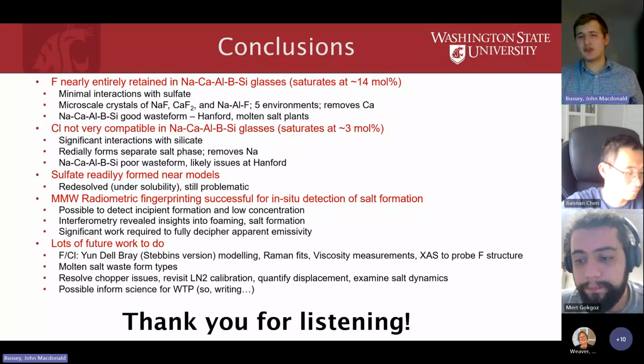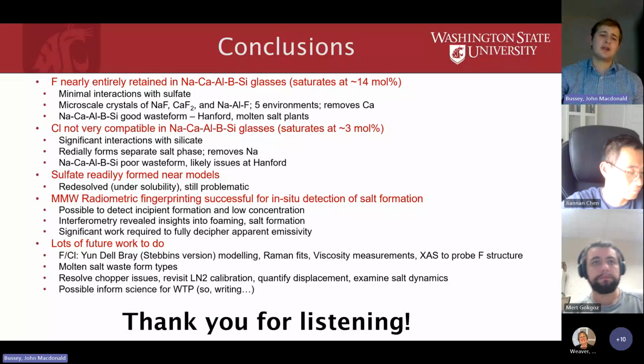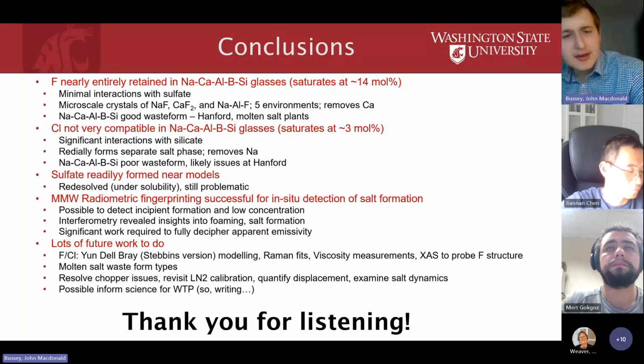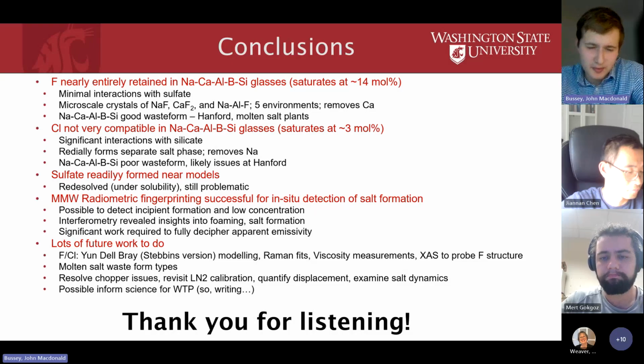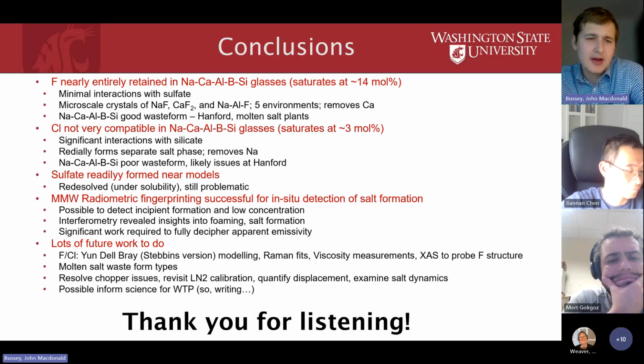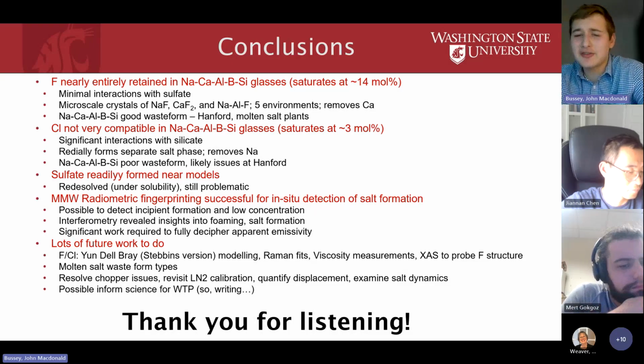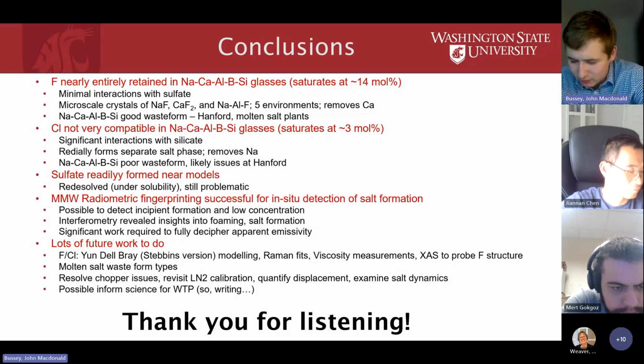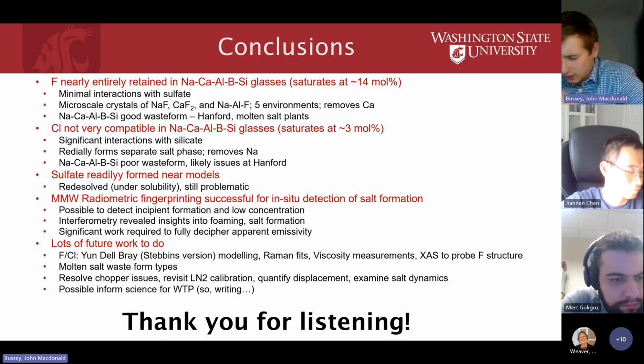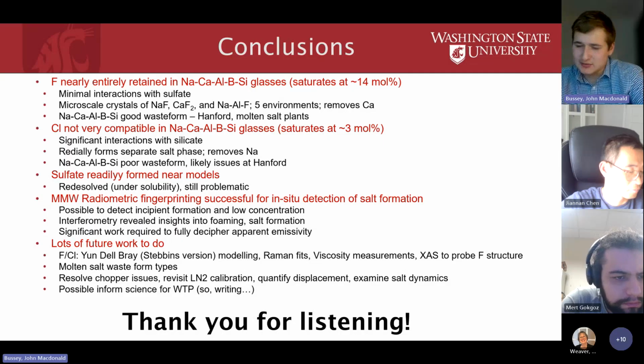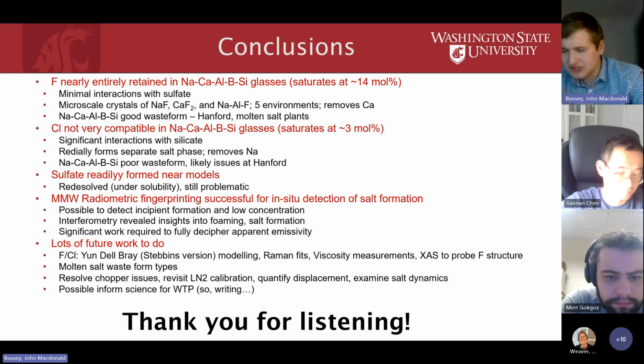So to conclude, to wrap up some of the things we've been talking about, for the fluorine in calcium, sodium, aluminum borosilicate glasses with sulfur, the fluorine is always entirely retained. So even at up to 25 mole percent, almost all of the fluorine stayed in the glass. Only 1% or less was volatilized, and none formed a surface salt, which is good.